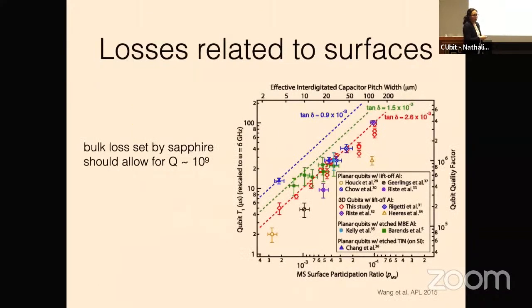There are a couple more things that we know about these losses. The first is that if you look at the bulk constituent components of the system, you should get much, much longer lifetimes, but you don't. And the other thing that we know is that if you make the devices smaller, they get worse. So this points to interfaces and surfaces as being a critical source of loss in these devices.